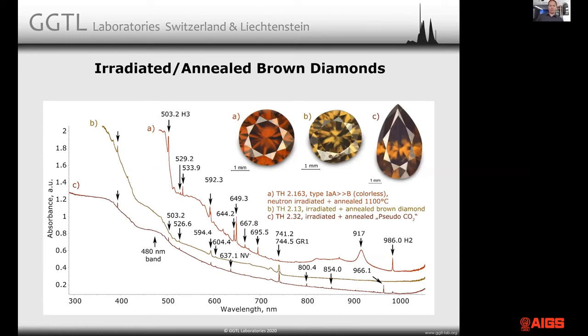That's why the stone stayed just basically brown. And then number C, that's one of those famous CO2 diamonds. Now this is a pseudo CO2 diamond. We have treated a range of those, and they actually never change. They don't change by HPHT treatment. They don't change by irradiation. You can induce some GR1 bands in it, but then you anneal it and nothing happens.